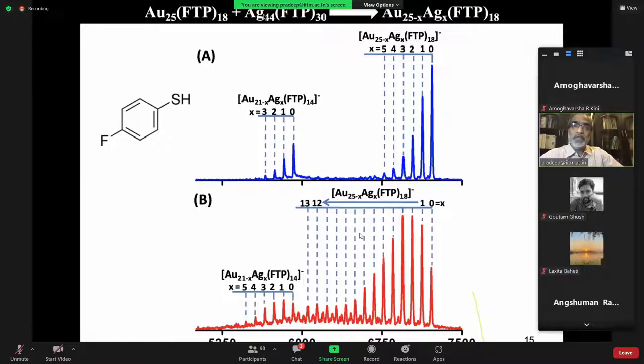If you mix this now, just after mixing, you see another peak. You get a series of peaks, and the difference between these peaks is the mass difference between gold and silver. So the composition of this cluster series that you see is this. Correspondingly, you have these fragments also. This is just after a few minutes of mixing.